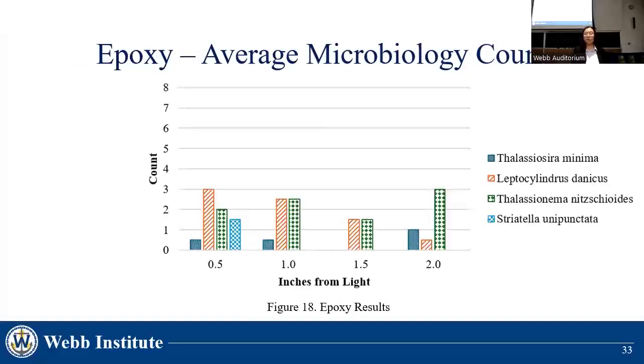The microbiology observed on the epoxy plates is shown in figure 18 above. In this case, the distances along the x-axis indicate the distance from the UVC diode, as well as the center of the plate. 4 types of microbiology were observed on the epoxy plates. The most common diatom found was the Thalassionema nitzschioides, seen an average of 3 times per plate.